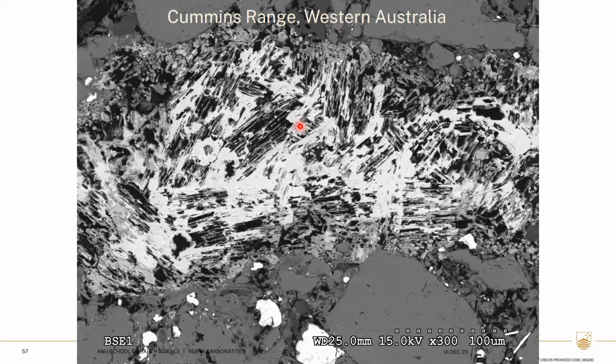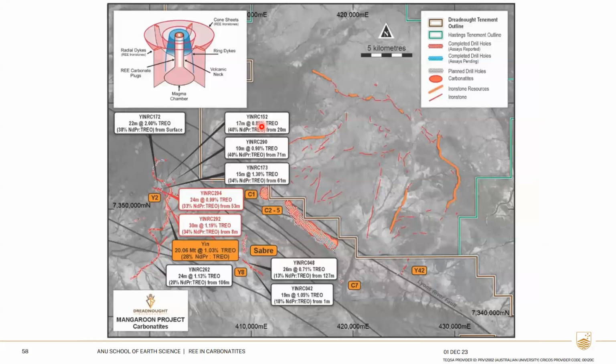What's the black platy stuff in there? In between, epoxy. It's like holes. Did you make your thin sections in water? Never. Never. It's something I learned very early on in my PhD on carbonatites, that never let them touch any water, ever, because things will disappear.